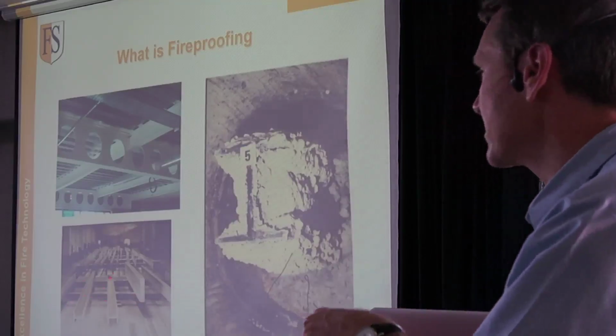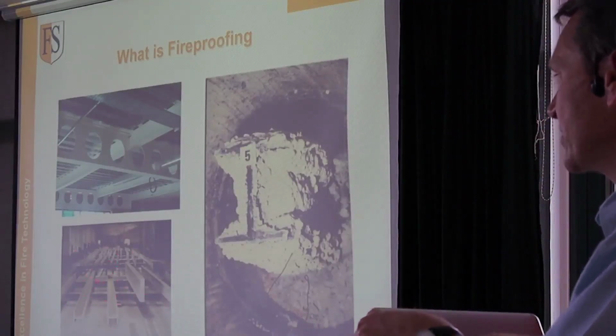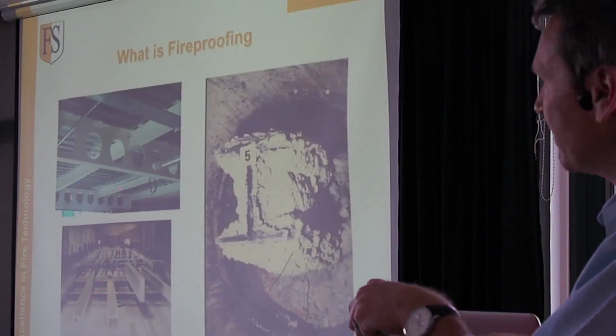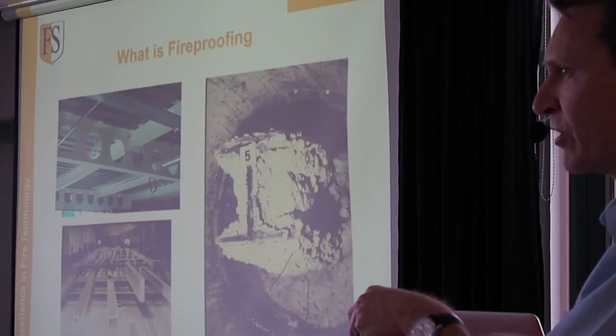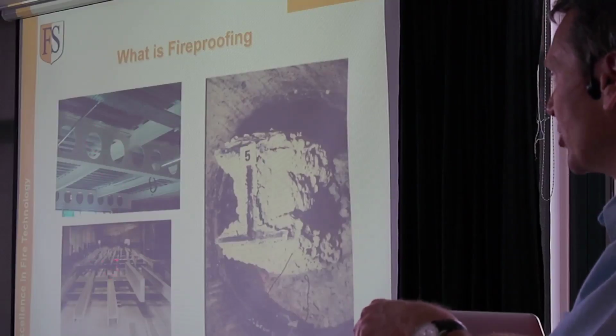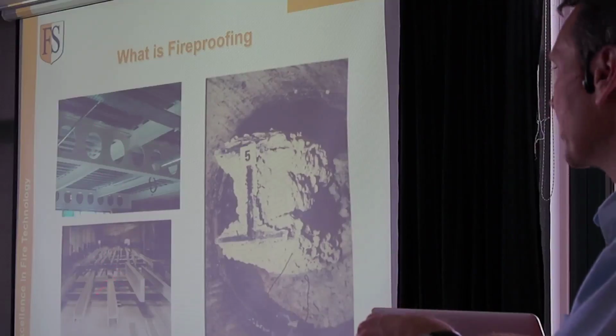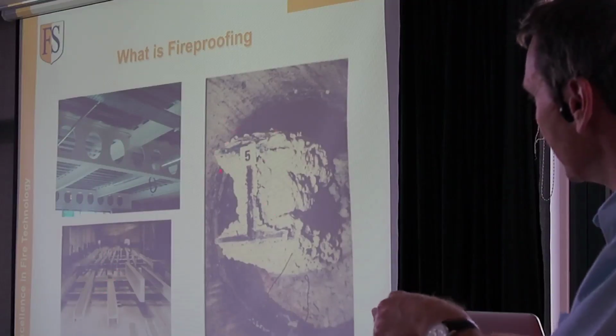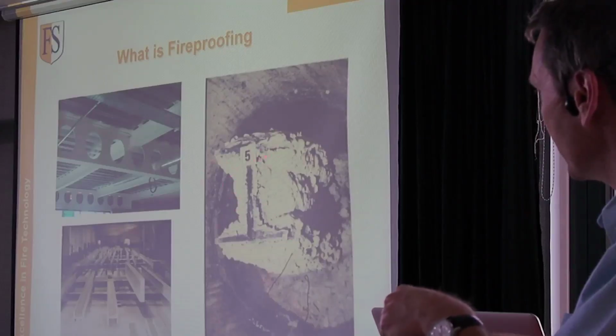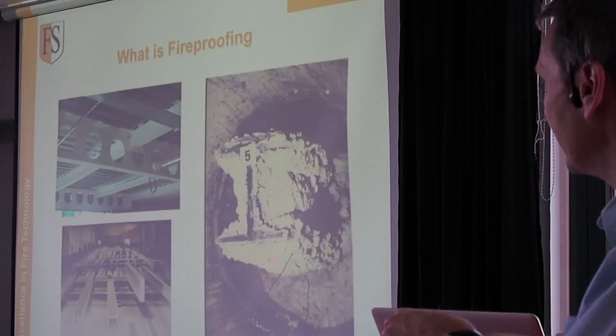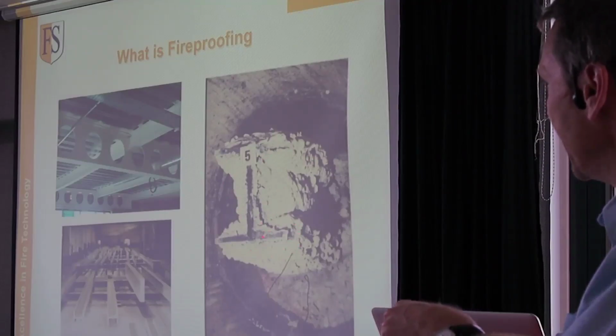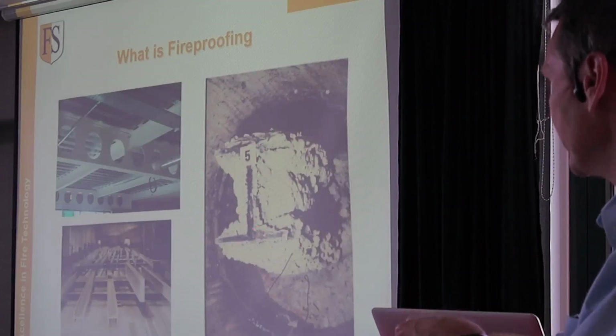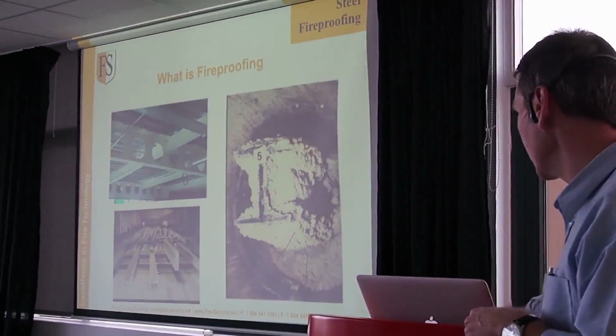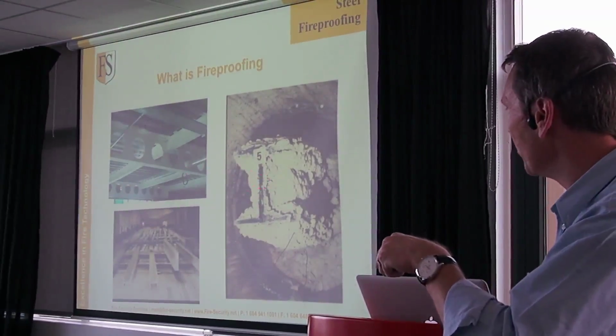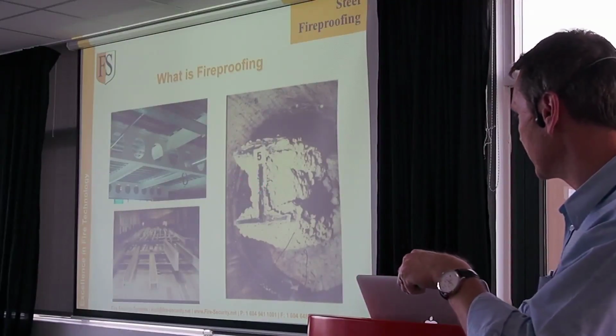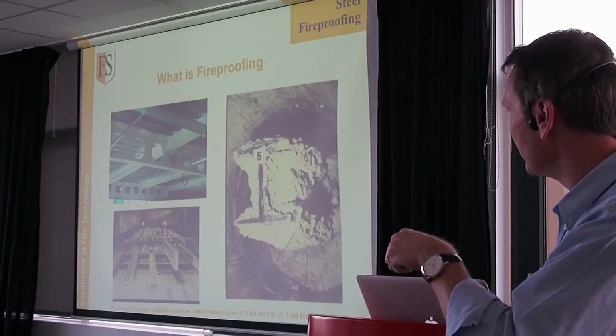This is actually a much easier and quicker application because this is effectively all at hip height when you're spraying. This can be done in scaffolding and everything else, so there's a lot of time. But this is done at a medium height and can be done at a very quick rate. And this column right here, this is what the coating looks like fully expanded under fire. You'll see that it's completely filled in and continuing the integrity of the steel for a period of time. And that will come out of something like about a 1.5 millimetre dry film thickness. So that section there would look like that under fire.